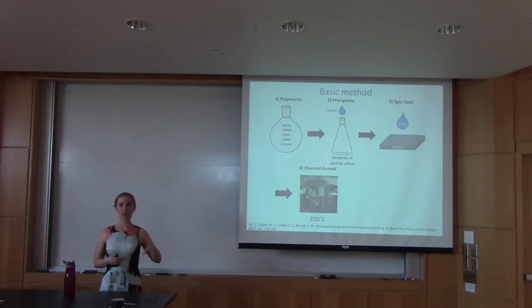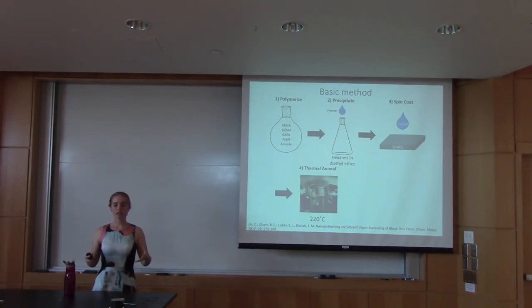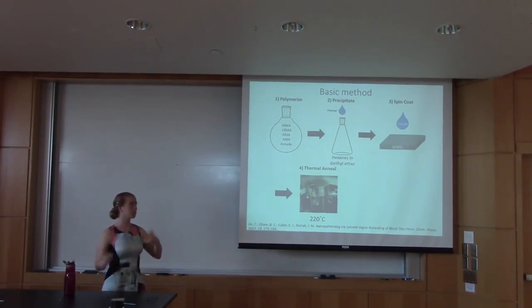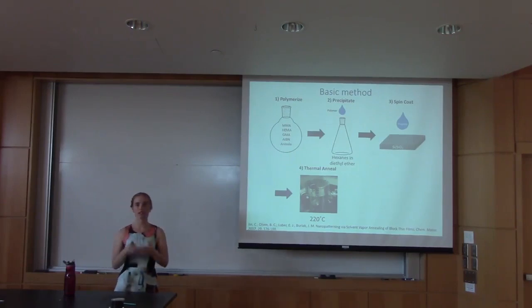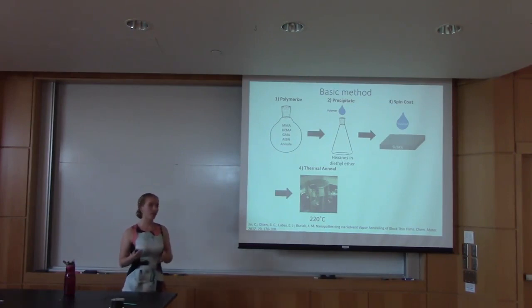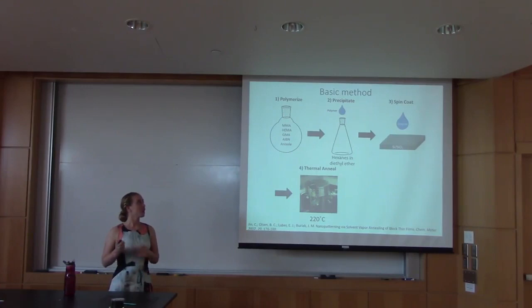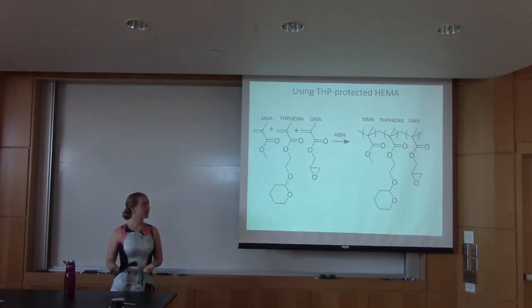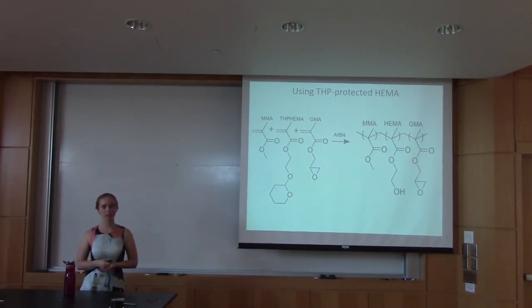This step is done in a vacuum chamber that heats up. Because we spin coated this polymer on top of this surface, it's kind of all disorganized, and heating this up in a vacuum chamber allows it to settle down into a more equilibrium position and be a little bit more ordered. We did this at about 220 degrees Celsius for 3 hours. And this is where we actually did this deprotection of the THP group. Through this thermal annealing, we deprotected this THP group into regular HEMA.